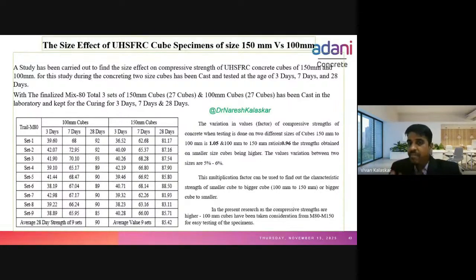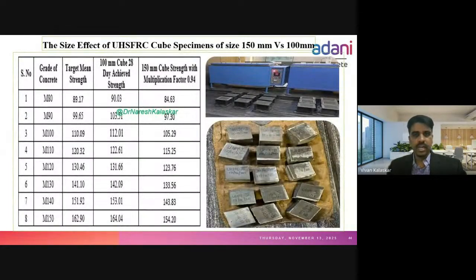So with this study, I have established two multiplication factors, which can be used by anyone in coming research. If you have casted 150 mm cubes of UHPC, and you want to convert those results into 100 mm, you have to use multiplication factor 1.05. Whatever compressive strength you are getting, you multiply with 1.05, and you will get the 100 mm cube results. If you have casted 100 mm cubes and want to convert into 150 mm cube, then you have to use multiplication factor of 0.96. So these are the multiplication factors you can use as per the requirements, and we have checked with the target mean strength.